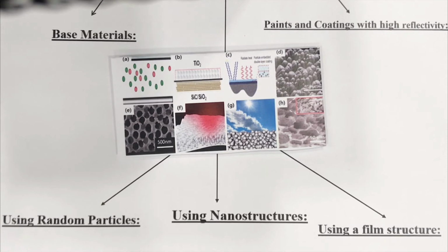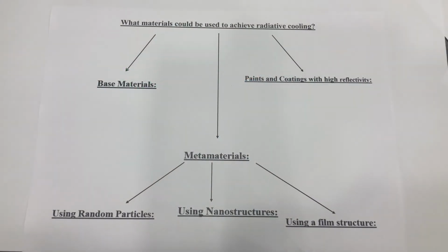One of the researches done in this area showed that using densely packed titanium dioxide particles on top of densely packed silicon carbide or silicon dioxide particles, all on an aluminum substrate, can be used for radiative cooling purposes. This design was able to produce an 8 Celsius reduction below the ambient temperature in a region with high humidity like Qatar.